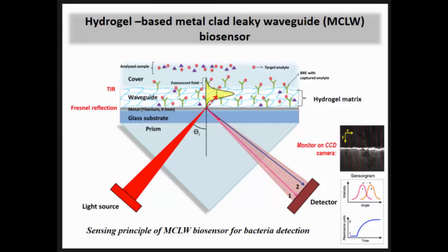We use LED light as a light source and a CCD camera to monitor the outcome. So for example, if there are any changes in refractive index inside the hydrogel matrix, it will change the resonant angle from position 1 to 2. Therefore, we can see the changes here and develop the result based on that.